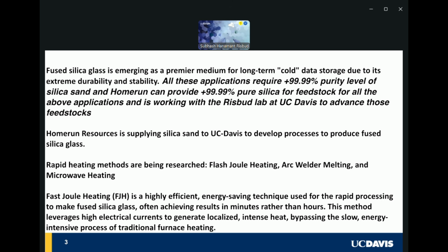But the applications right now that we are working on are to develop a process to rapidly produce silica glass. And glass is my favorite subject for years, since my days with Dick Fulrath at Berkeley and subsequently at Illinois and Arizona, where we worked a lot with growing quantum dots in glasses, and also silicate glasses and silica particularly. So the 3 methods I want to talk about, which we are researching, is to reduce significantly the amount of time it takes to make the fused silica glass from the raw sand, which is basically clumps of raw material from the earth. And the 3 methods we have tried, and not all of them have been finalized to perfection at all. One of them is flash Joule heating, and the second one is arc welding, and finally microwave heating. So I will talk about all of these methods a little bit.